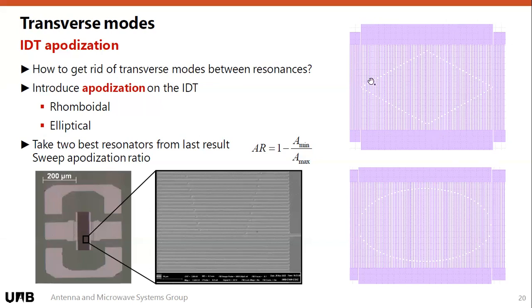In this case, at the center we have the maximum overlap between the IDT fingers, and at the extremes you have no overlap. So this is what we call the apodization ratio. In this case it would be 100%. If you have a 0% apodization, you have no shape. You have both cut lines facing each other at each of the sides of the resonator.